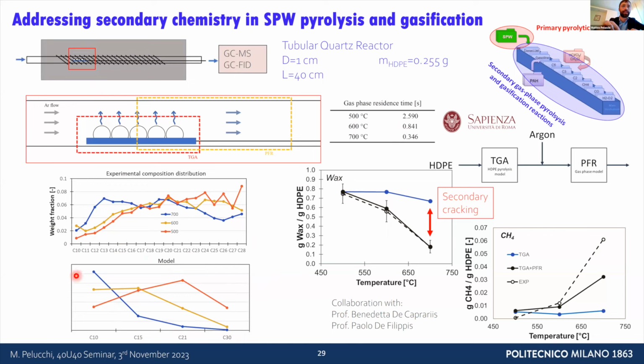But at least you see that by increasing temperature, you are expecting more lower molecular weight fragments. And as you decrease temperature, the fragments you form will be higher, so you will have a higher amount of waxes.